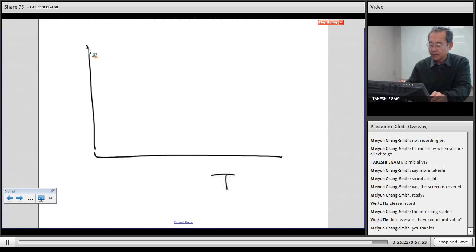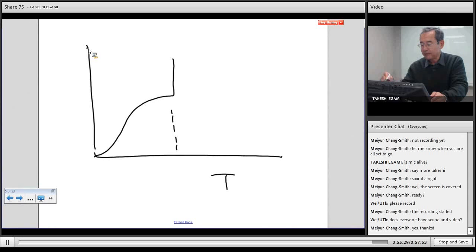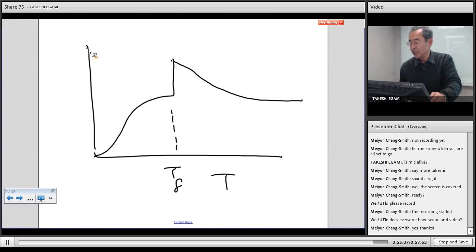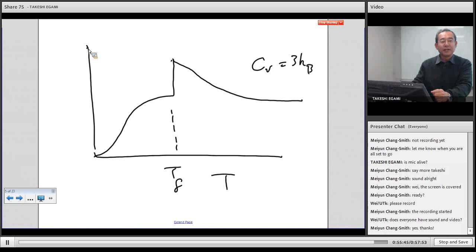In spite of that, if you measure specific heat, then it goes up like that, and then jumps at a temperature called the glass transition, but it comes back again, and then satisfies the so-called Dulong-Petit law, which is that CV is equal to 3k. So this was for a long time sort of a mystery, why this Dulong-Petit law is observed even though there is no phonon. And this localization gave the answer. The phonons are completely localized, and there's a different mode existing in high temperature liquid.